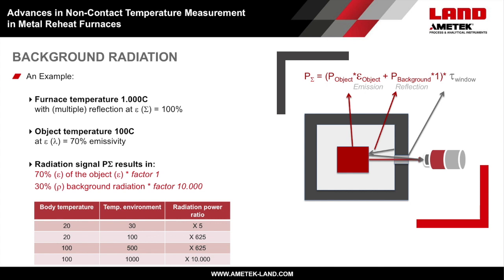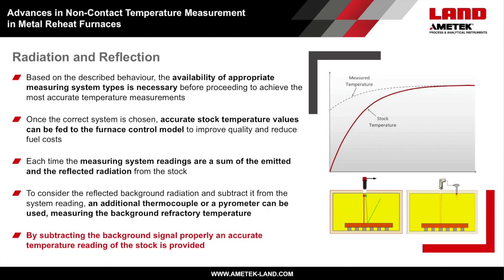So this can be an essential influence to the temperature reading of the stock in the furnace. This is why we need to compensate for the reflected background radiation to enable an accurate object temperature reading. Based on the described behavior, it is essential to use an appropriate measuring system to achieve the most accurate stock temperature measurements, which can be fed back to the furnace and process control system.